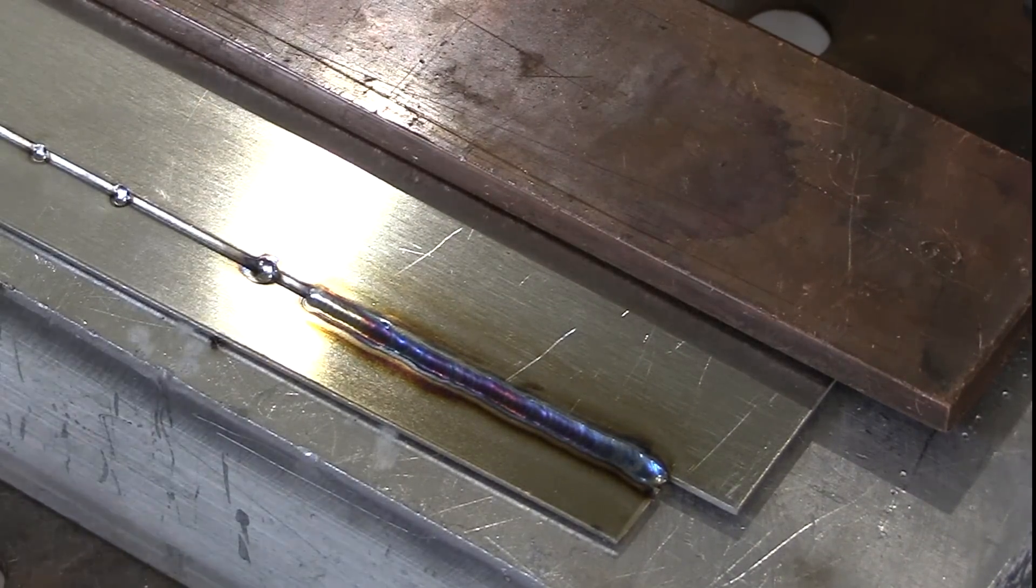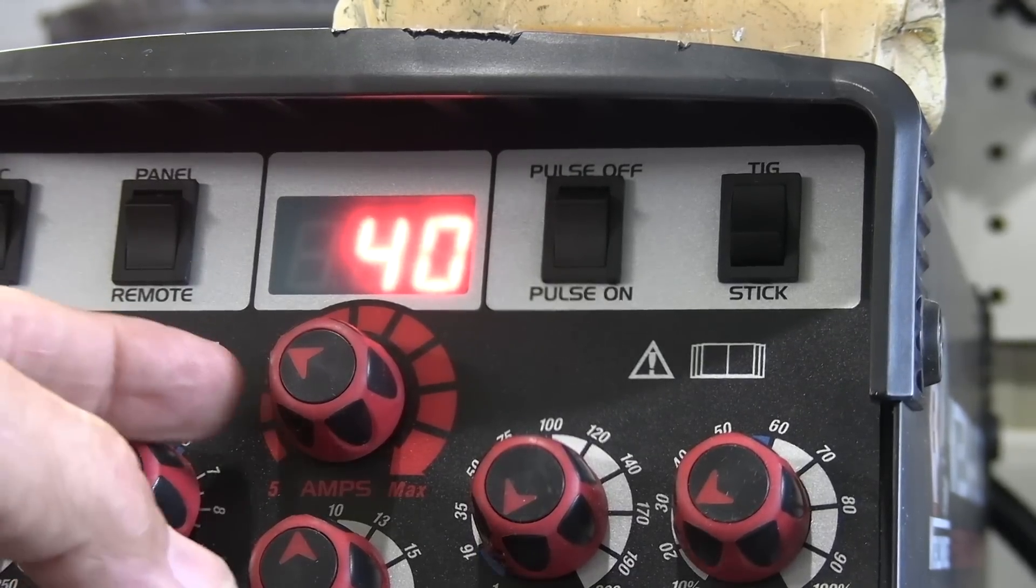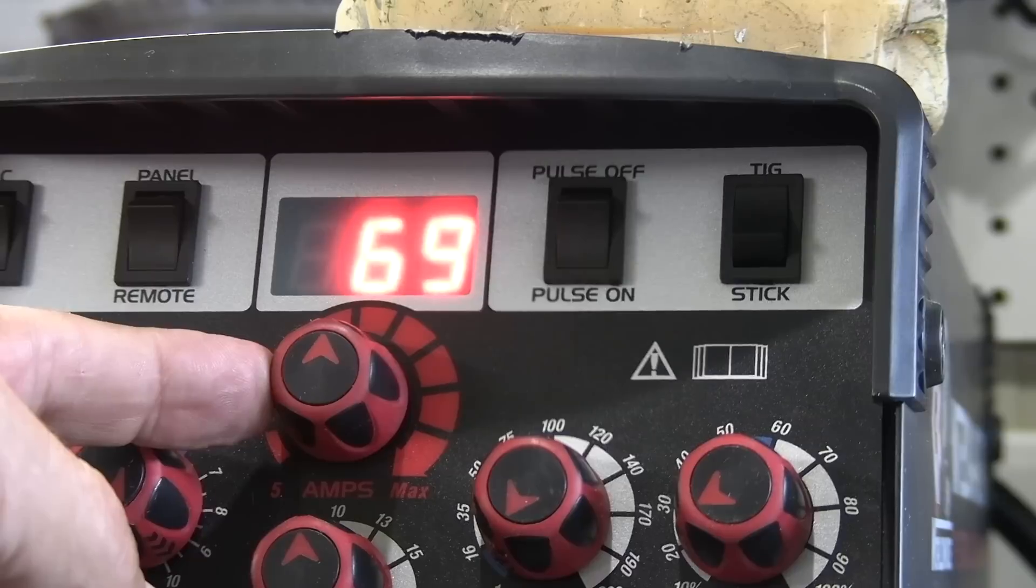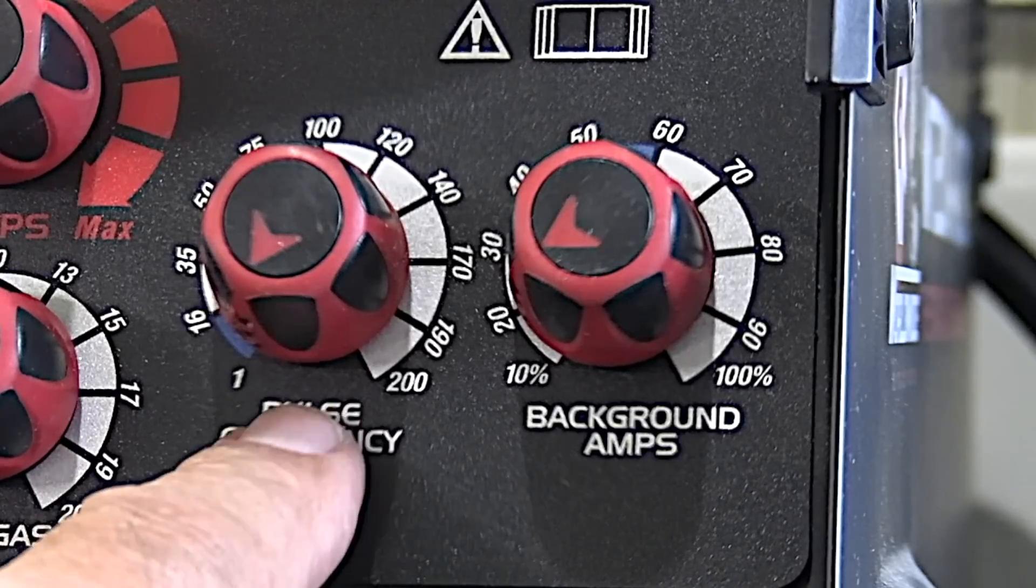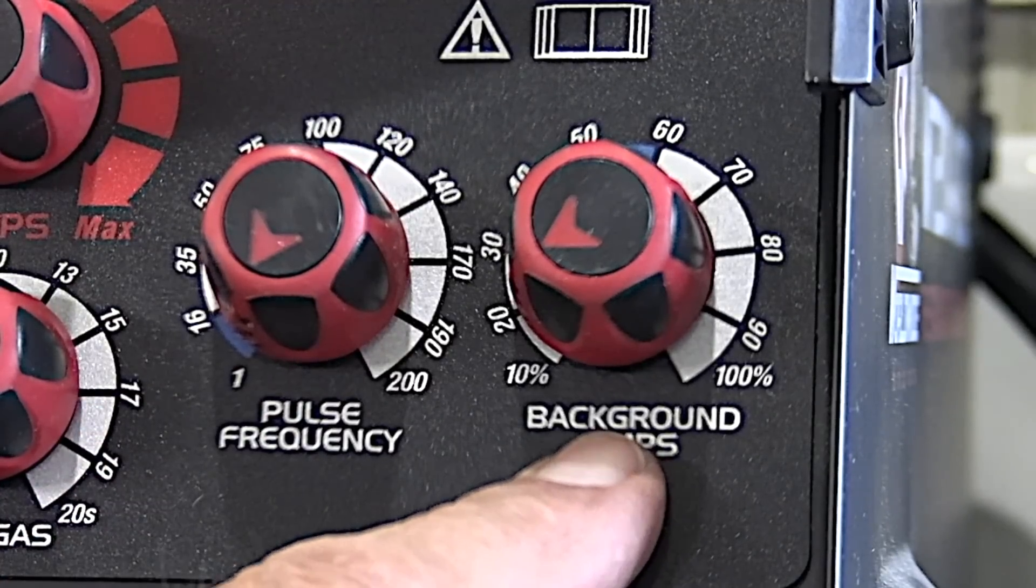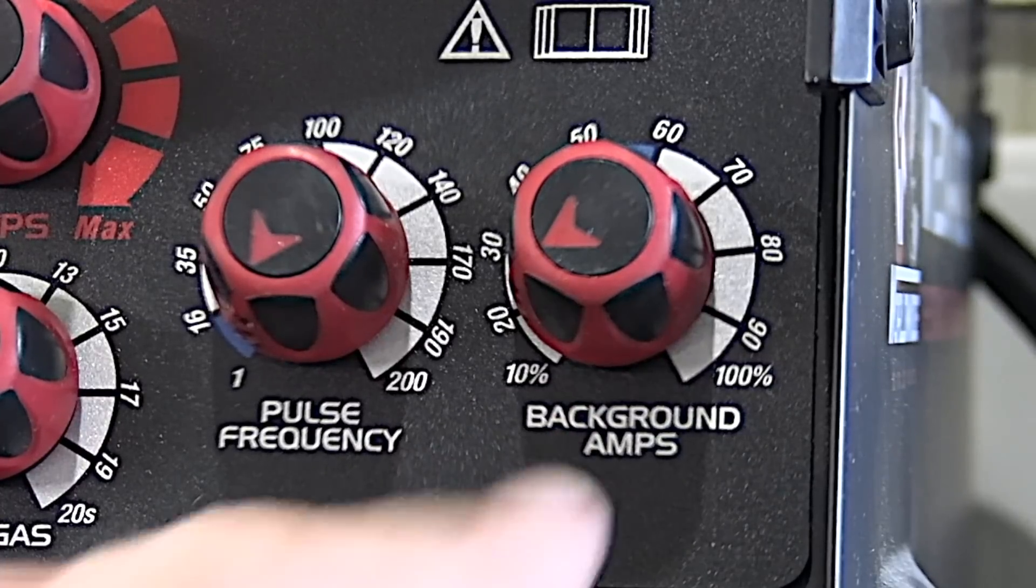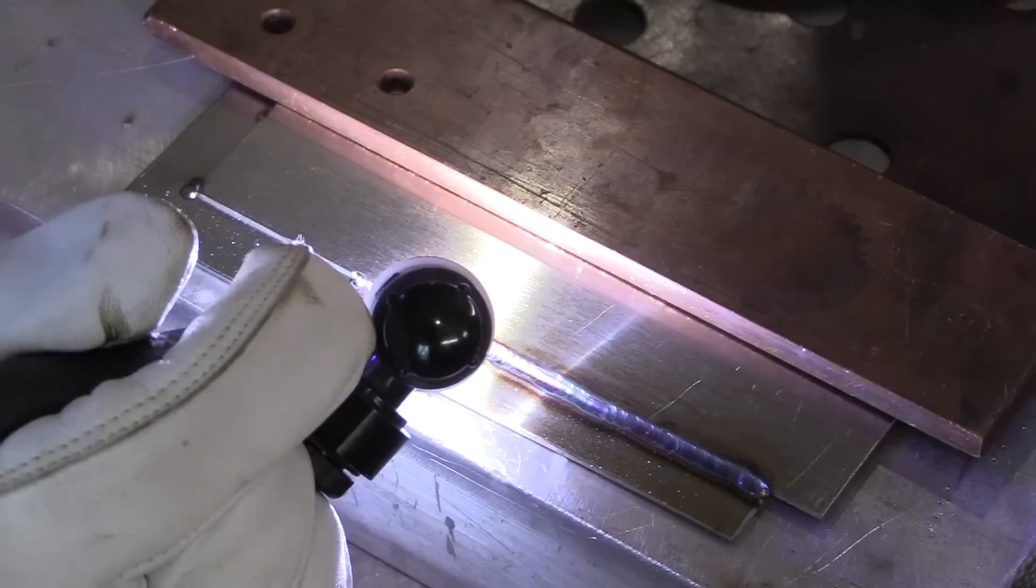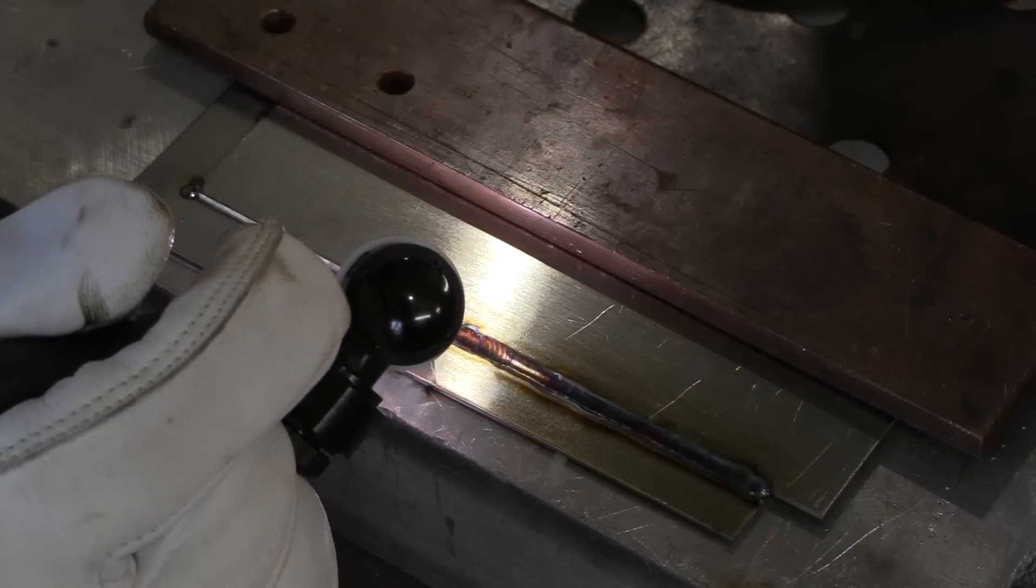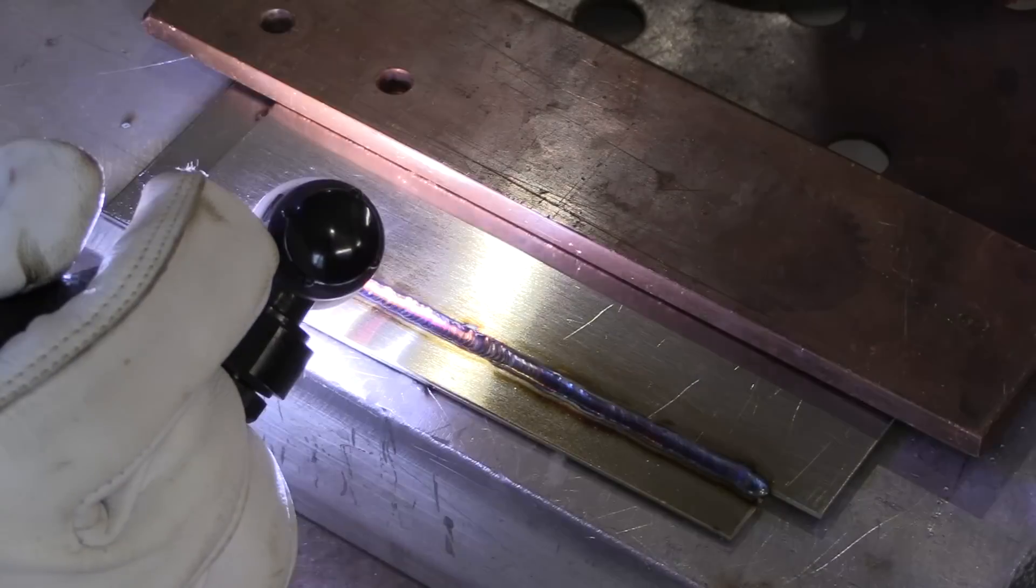Now we're going to switch over to some pulse settings. Pulse switch on. I'm going to have to go up on the amperage—you always do when you use pulse. It needs more amperage set on the machine, and I found out that that setting right there was just about right. I'm going for two pulses a second here. That takes a little bit of trial and error on this machine at about 20% background, 20% background current, and the pulse width is fixed at around 50% I think. So two pulses a second here, it's pretty close, and actually that's a really darn good setting for this. One pulse a second was a little bit too slow, kind of choppy. Two pulses a second lets you kind of put a fairly nice set of ripples on there with no filler metal.